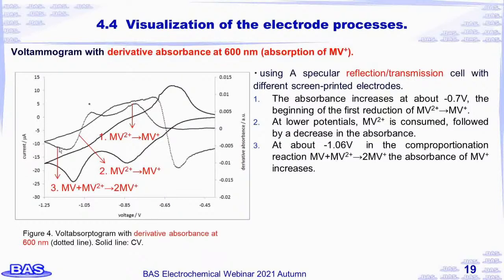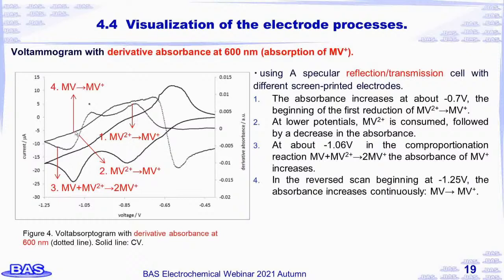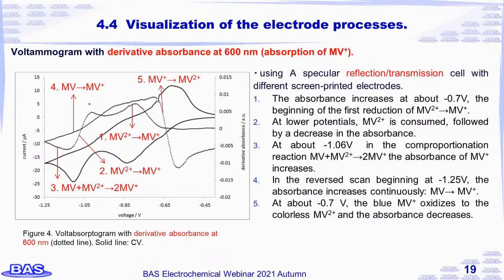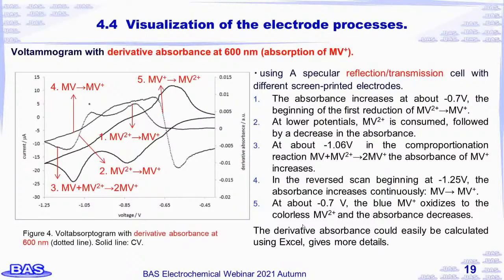At about minus 1.06 volt, in the comproportionation reaction 3, the absorbance of the monovalent cation increases. In the reversed scan beginning at minus 1.25 volt, the absorbance increases continuously by reaction 4. At about minus 0.7 volt, the blue monovalent cation of methylviologen oxidizes to the colorless divalent cation and the absorbance decreases.